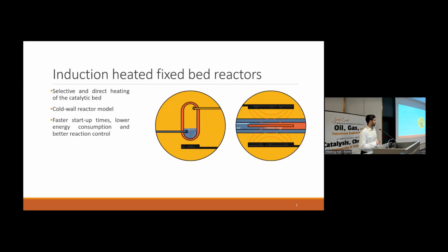The main idea in our lab and in other labs right now is to use induction with heterogeneous catalysis. So the idea is to use induction in order to heat our catalysts directly inside the reactor. So we would be starting from the hot wall reactor model, where we're heating the walls of the reactor and transferring energy from the reactor to contents inside and then into our reaction medium, to the reactor, where we bypass our reactor walls and we directly heat what's inside.